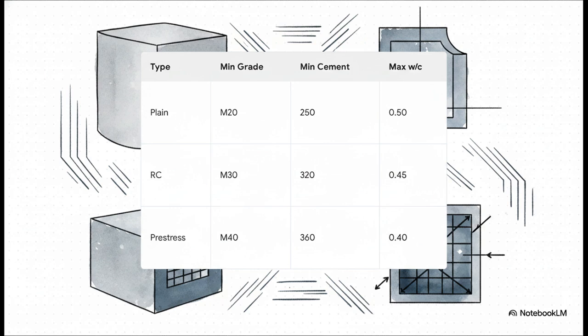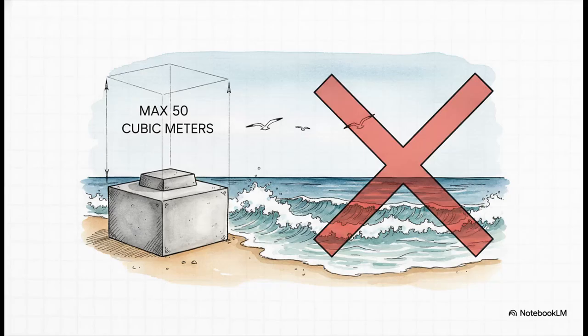So, for plain concrete, you need a minimum of M20 grade with 250 kilograms per cubic meter of cement and a max water-to-cement ratio of 0.50. Step it up to reinforced concrete or RC, and boom, it jumps to M30, 320 kilograms of cement, and a tighter 0.45 ratio. And for pre-stressed, it goes all the way to M40 grade, 360 kilograms of cement, and a super tight 0.40 ratio. But hey, watch out for this exception right here.